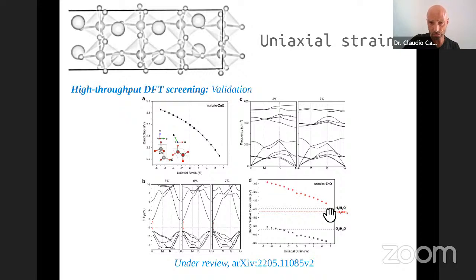And this is where we specifically calculated the band alignment, the top of the valence band and the bottom of the conduction band, under these strain conditions. We find that these lines look pretty linear, which is consistent with our simple piezoelectric plate capacitor model. And the numerical value that we get for this slope is compatible with what we got from our alpha value.